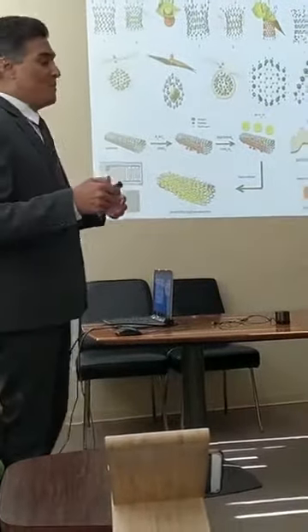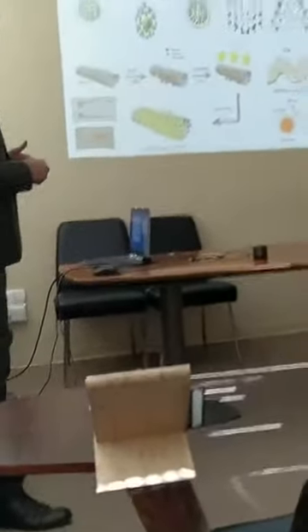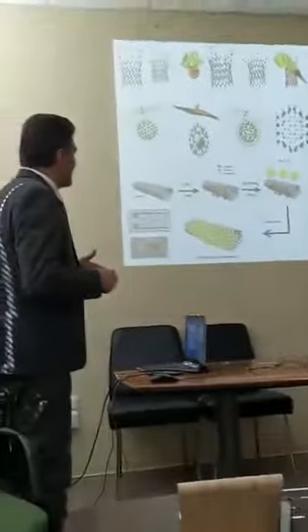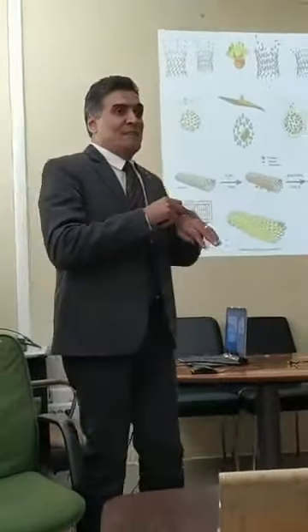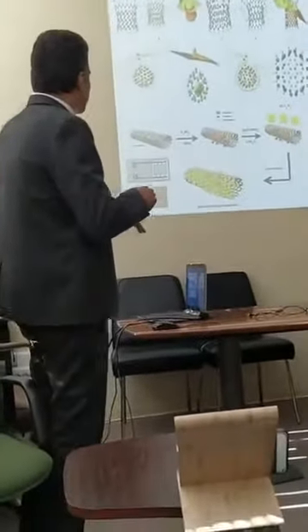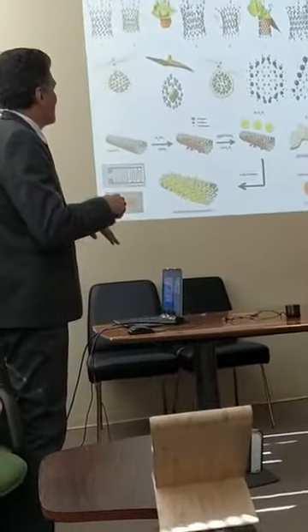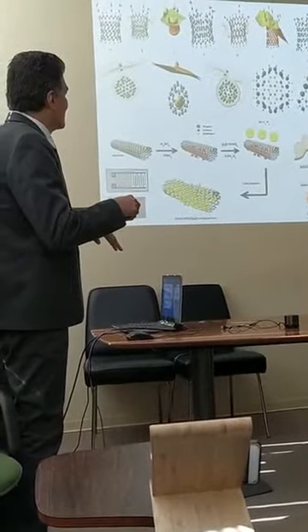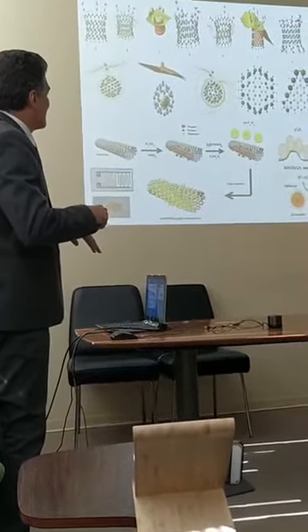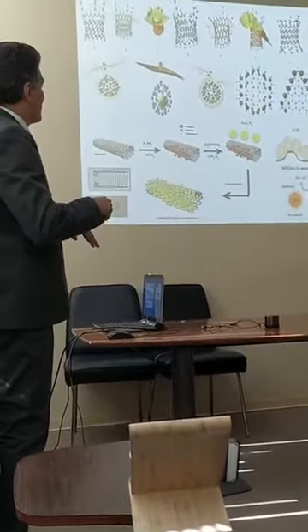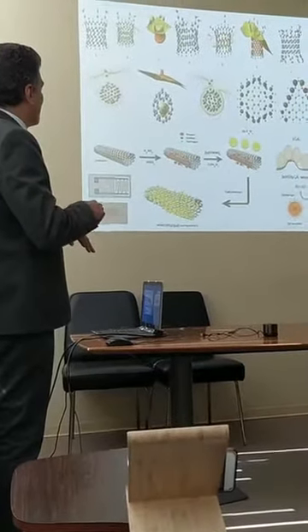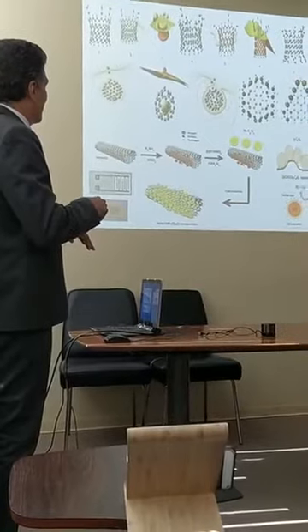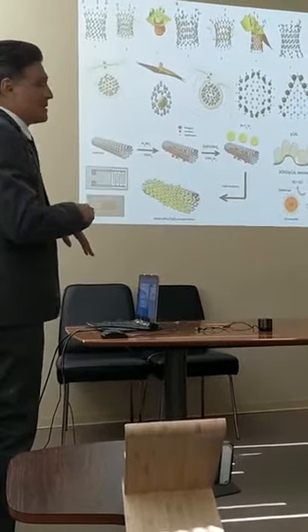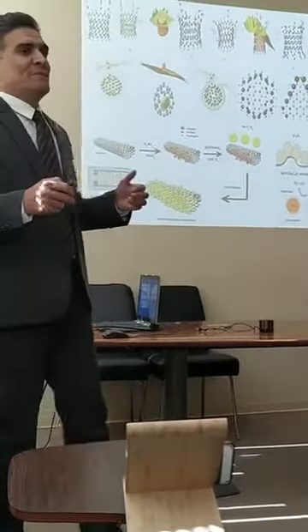They are with our group, for example. We said if you are going to make zinc oxide decorated over carbon nanotubes, you have to make some kind of activation for the surface, and there was a source of zinc for this, and make the interaction finally to put the zinc oxide as a nanocomposite on the surface of the carbon nanotube, and you get an interdigitated gold electrode, and this is finally our sensor.